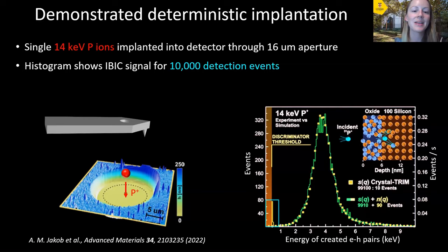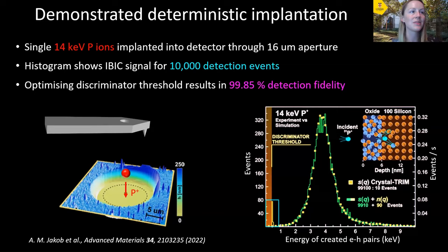And because the energy of the generated electron hole pairs varies due to the random nature of the donor ion stopping processes in the oxide and the silicon, you get this distribution of energy of created electron hole pairs. And by optimizing the noise threshold of the detector, we could achieve a single ion detection fidelity of up to 99.85% for our single phosphorus ions, which we're very excited about because this means we will be able to implant our donors with a very high confidence and know that we've achieved single ion implantation at each site that we want to implant our donors into. That gives us promise for moving forward to making scalable arrays of donor qubits.